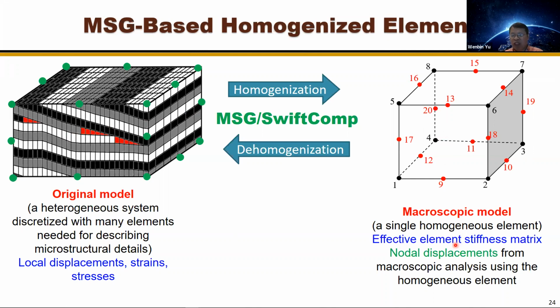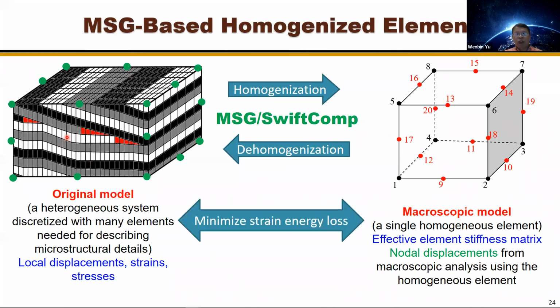It's not a material stiffness matrix anymore. For example, for a 20 node element, you're talking about a 60 by 60 stiffness matrix. And after you've done the global analysis, you do a dehomogenization and get all the local stress within the original material. You apply your failure, whatever local buckling criterion, at that level. So what we need to do is minimize loss of energy between these two systems.